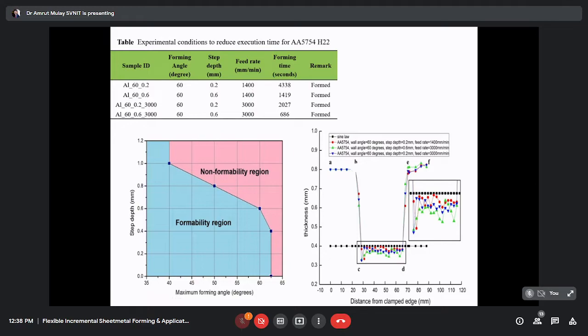Now we know from our previous study that feed rate has more influence on the time calculation. So you see that step depth and feed rate give you the reduction of time. Now we had 0.2, 1400, and here we see a drastic increment in the step depth while keeping feed rate constant. Now you see 0.2, 0.6, 1400, and here 1400 to 3000, because the machine capacity is 3000. After 3000 per minute the machine won't work. So by seeing the capacity of the machine, we selected it. It is a CNC machine, so you have to see the limitation of the machine. Within that limitation only you have to work. So 1400 to 3000, and at 3000 we took 0.2 and 0.6.